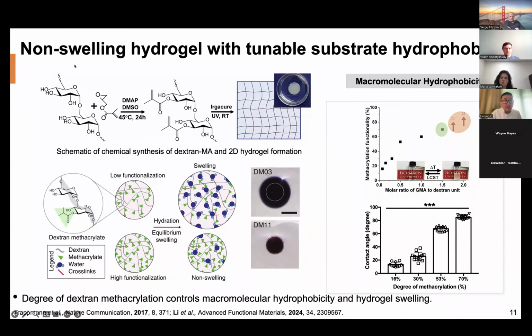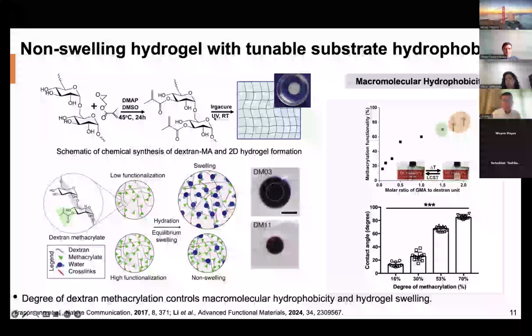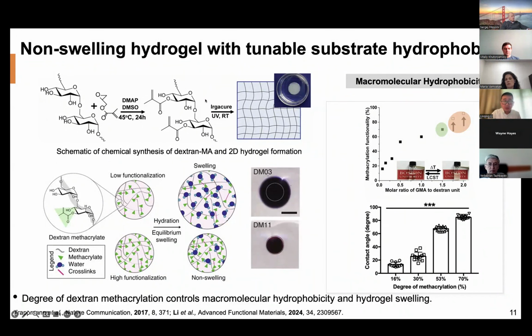The hypothesis is that when you modify with glycidyl methacrylate, you change from a relatively hydrophilic polymer, whose hydroxyls form hydrogen bonds with the water environment, to a modified one. If you gradually add more methacrylate to the dextran backbone, it goes from a hydrophilic monomer to hydrophobic compartments. At higher modification, you can generate a relatively hydrophobic modified dextran. And once you mix different ratios of methacrylate,